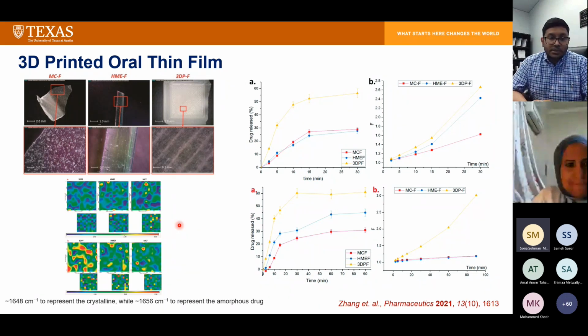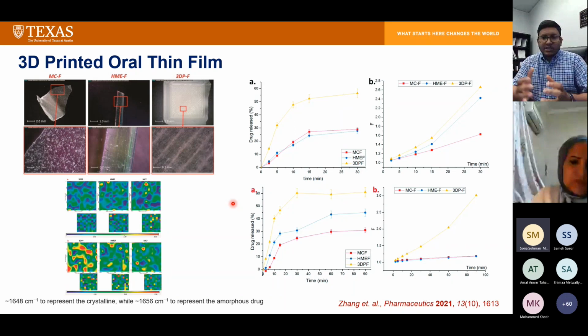And most importantly, as can be seen from this photograph, drugs were present in their amorphous form. As a result of that amorphicity, when we did the dissolution studies in both simulated saliva as well as the phosphate buffer, we found that the drug was released faster from our 3D printed film compared to the other traditionally manufactured films. So that shows a good example of how 3D printing can be used for enhancing the dissolution rate of the drug by forming amorphous solid dispersion. We also published this paper recently and it is available as well.